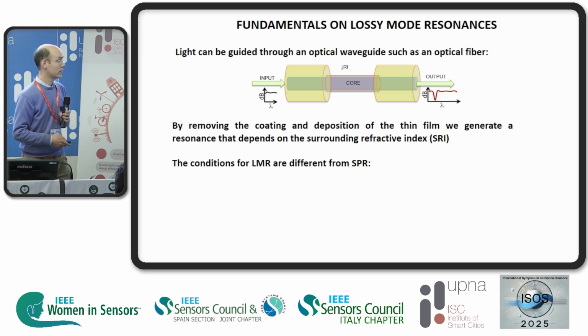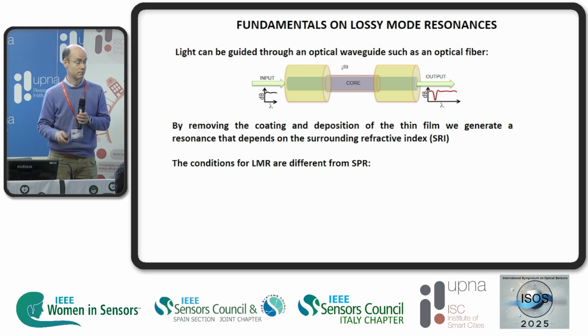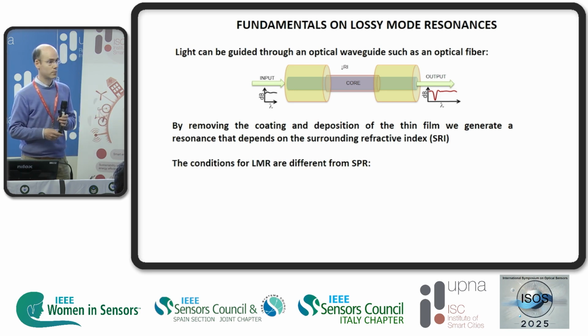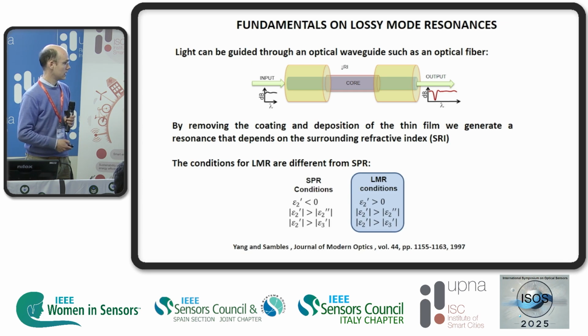The conditions for LMR are different from surface plasmon resonance. Nowadays, I think more people are aware of this, but in the past there was some confusion between both phenomena. There is a publication from 1997 where we can differentiate the conditions in terms of the permittivity of the thin film, the real part and the imaginary part. We can summarize these rules by saying that the LMR conditions correspond to materials that are rather dielectric, metal oxides, polymers, and SPRs are generated better with metals, typically silver and gold.